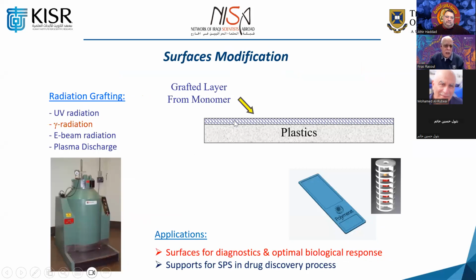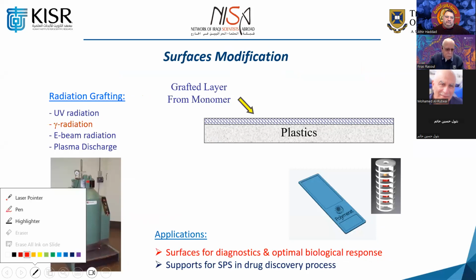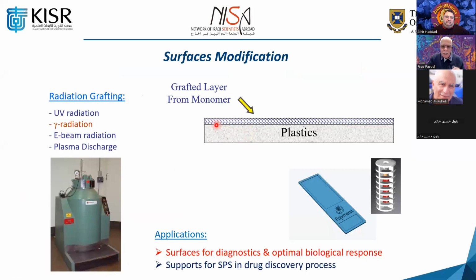What we used, actually, is a variety of different techniques in grafting polymers. For example, for styrene and polyacrylic acid, mainly we used gamma radiation. And this is a picture of the gamma radiation. You have your plastic, and then you put a uniform layer of another polymer. If we have polypropylene, on top of it we put a layer of polystyrene, for example, or polyacrylic acid, and then we will be able to functionalize it. We make it aminomethyl polystyrene, where we have an amino group, and this amino group can be used for further functionalization.